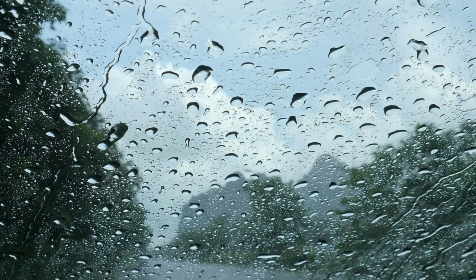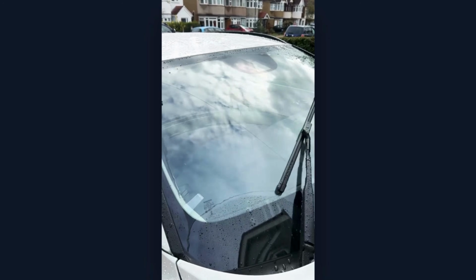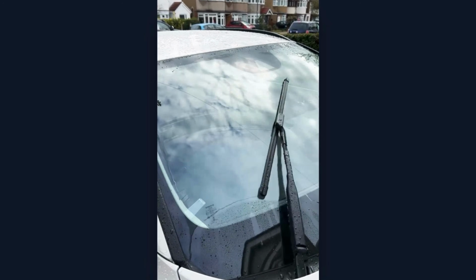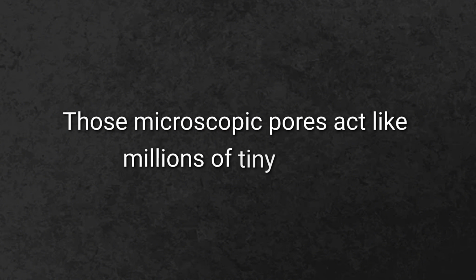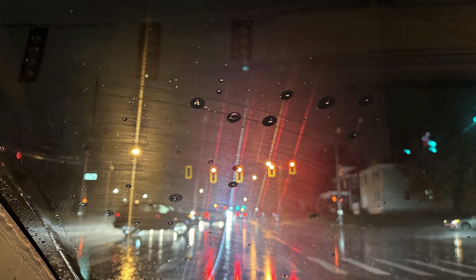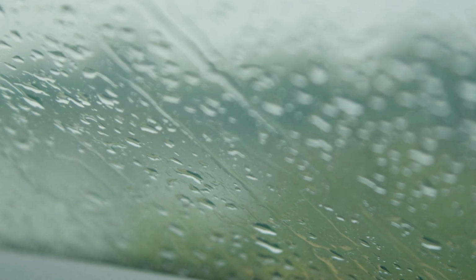But when a water droplet lands on that surface, it does not just sit on top. It falls down into those valleys and locks in. That is why water on untreated glass spreads out into large, flat drops that cling to the surface and smear when your wipers hit them. Those microscopic pores act like millions of tiny prisms, splitting and deflecting light in all different directions. That is the glare you see at night. That is the haze in heavy rain.